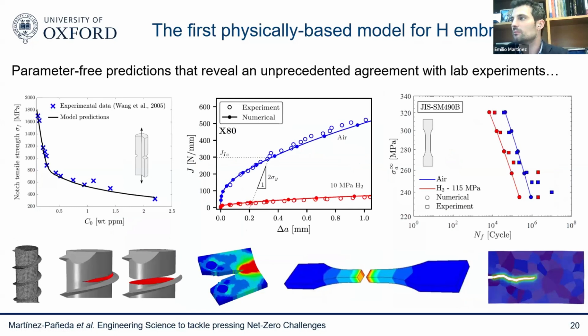You can see some various calculations here, some representative results, and comparisons with experiments. You can see here, again, those models have no fitting whatsoever. All the parameters we know before we run a simulation. And you can see these are experiments on notched tensile strength of high-strength steels that were pre-exposed to hydrogen. The symbols are experiments, the line is the prediction of the model, a very good agreement over a wide range of hydrogen concentrations. These are those pipeline steels that I showed you before.